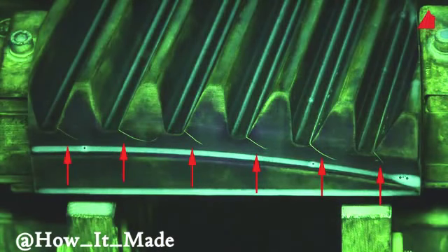The visible cracks are so-called fatigue cracks. They have been generated during the operation of the gear drive due to a mismatch of the gear wheels.